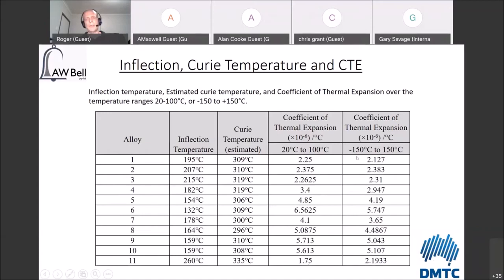But then when we look at the minus 150 to plus 150, especially alloy 1, which was the specification that was correct for the ISO alloy, coming in around about 2.1, actually outperformed the wrought material over the same temperature range. So this was extremely encouraging. And really tended to suggest, well, we'd actually done it. We'd managed to find something that would achieve the correct sorts of thermal expansions, and it was going to be castable as well. So we found that the inflection temperature was reasonable, up around 195 degrees, and the Curie temperature, or estimated Curie temperature, around 309 degrees Celsius.